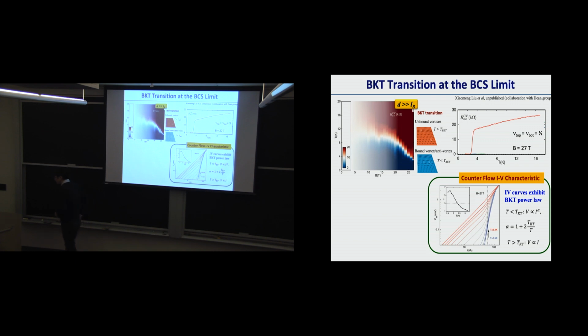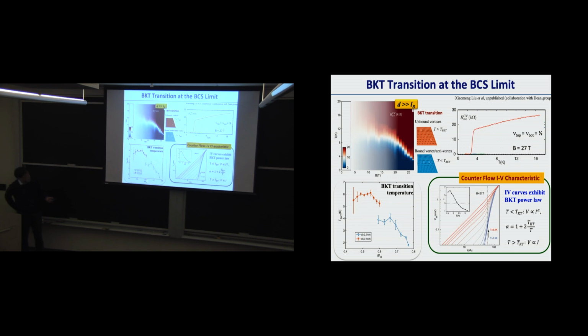We can actually plot out how this KT transition temperature can be modulated by the magnetic field. The relevant length scale, relevant energy scale, is just converting this magnetic field into magnetic length and comparing it with the size of the exciton, in this case the interlayer separation.